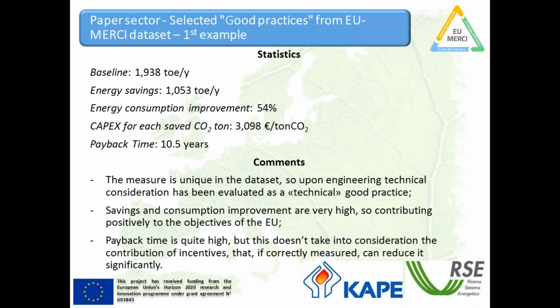In this case, we had just one measure, so we don't have average, we have the direct values. The baseline is around 2,000 tons of oil equivalent with savings around 1,000, so an energy consumption improvement that is more than 50%. The capex is quite high over the saved CO2, is around 3,000 euros, and the payback time is 10.5 years. This measure has been found only once in our dataset, and it has been identified as a technical good practice. Savings and consumption improvements are very high and contribute positively to the objective of the European Union in terms of energy efficiency.